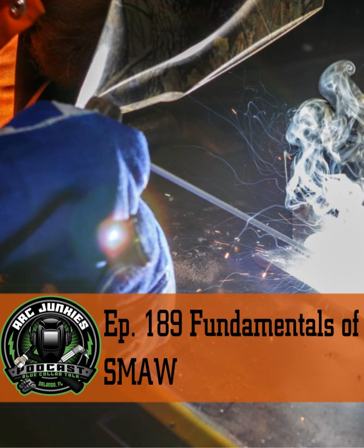Now, if you're getting to that mark after 10 seconds, you're going too slow. If you get to that 1-inch mark around 4 or 5 seconds, you're probably going twice as fast as you need to. So you got to slow down. Faster travel speeds are going to result in a high, ropey bead profile with little to no penetration. So if you're welding along and you look at your pass, and you're like, damn, it's high, it's ropey, it's not really tied into anything, that's a good indication that you went too fast and you need to slow down.